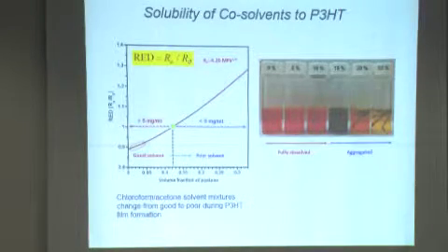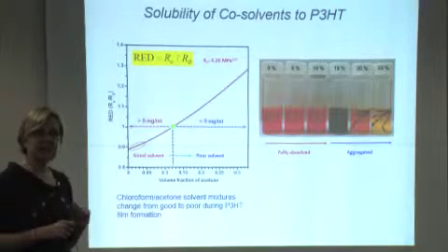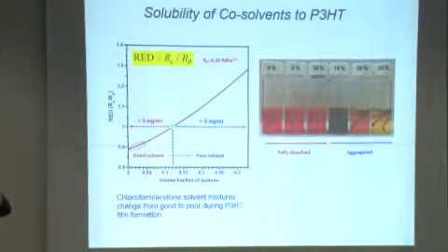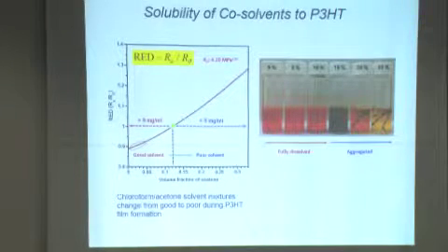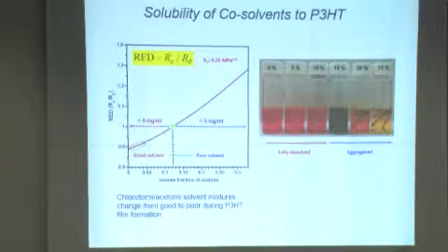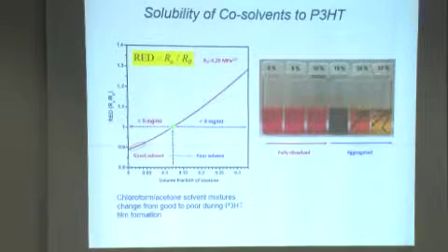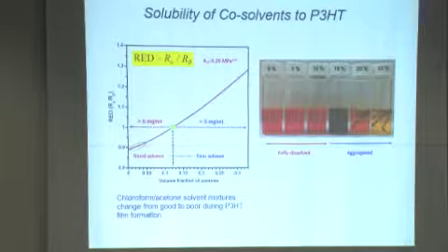So if we look at the solubility of co-solvents for P3HT, certainly the chloroform acetone mixture starts off as a good solvent, ultimately ends up as a poor solvent, so that since it is a binary mixture and the solvents can hydrogen bond, as the more volatile solvent is evaporating, there's an increased concentration of the poor solvent in the good solvent, and ultimately we end up with a poor solvent. That changes how the polymer behaves in that solution, and then that impacts the device performance.